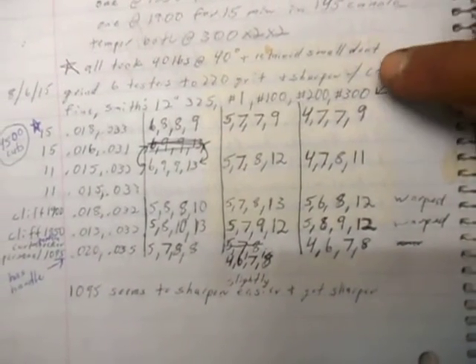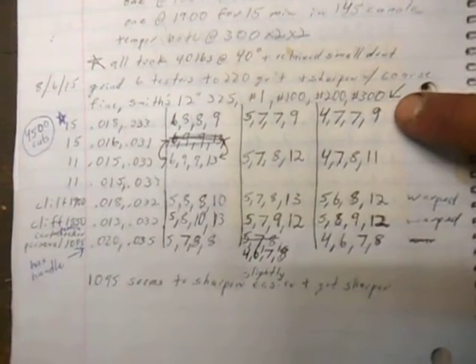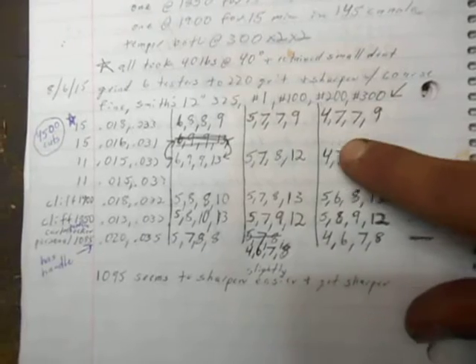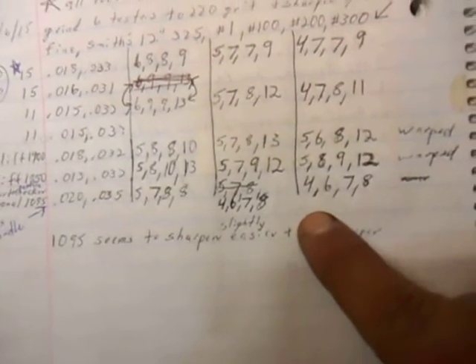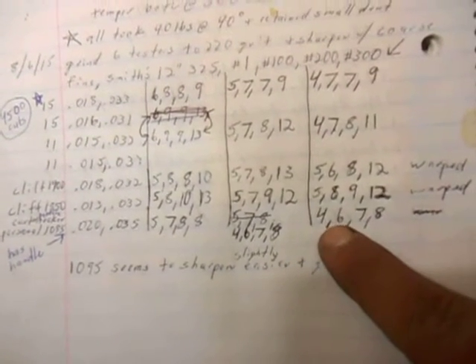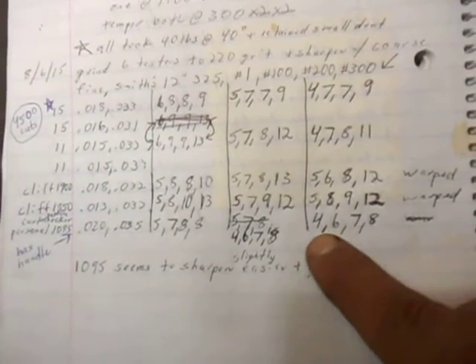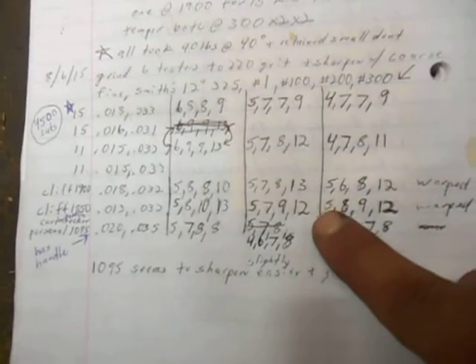But anyways, you can see that the best one was the 15-minute single quenched, tempered at 300 degrees for 2 hours, and do that twice. Took 4 pounds for the first cut, 9 pounds for the 300th cut, for a 5-pound gain over 300 cuts in that rope. That's roughly the same as what my 1095 was doing. My 1095 blade only gained 4 pounds over 300 cuts. But I only did three runs with each knife. If I did up to six runs, that would tell a much better story. But anyways, so that's the cutting test.